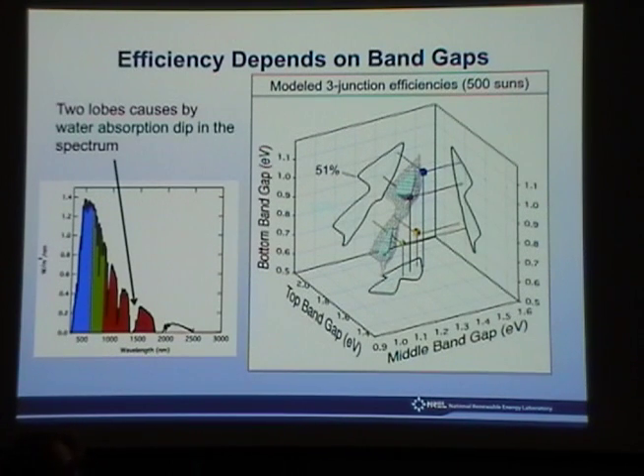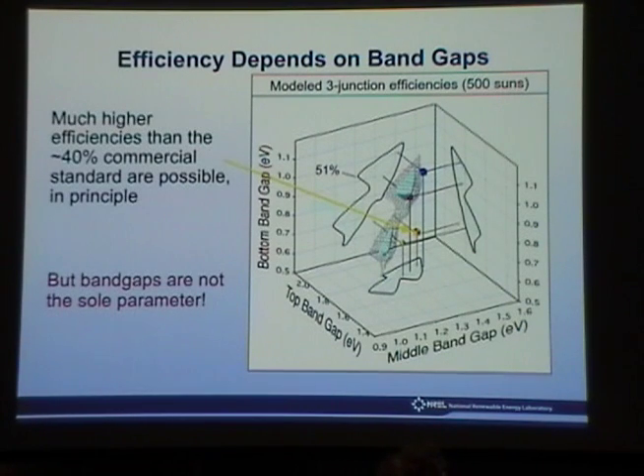Efficiencies are more or less comparable, but they do point to different technologies. The germanium-based devices all focus on this lower lobe because the band gap of germanium is down here, below the water dip. So the symbols on this graph represent different champion cells that have been commercialized over the past 10 years or so. The yellow one is this commercialized germanium-based cell that I mentioned on the previous slide, and I'll talk about the other ones in a minute. You can see they're all kind of far from the optimum, and even in efficiency, there's plenty of headroom between the 40% or so efficiencies that we've measured and the theoretical maximum. So part of it is that band gaps are not the sole parameter.